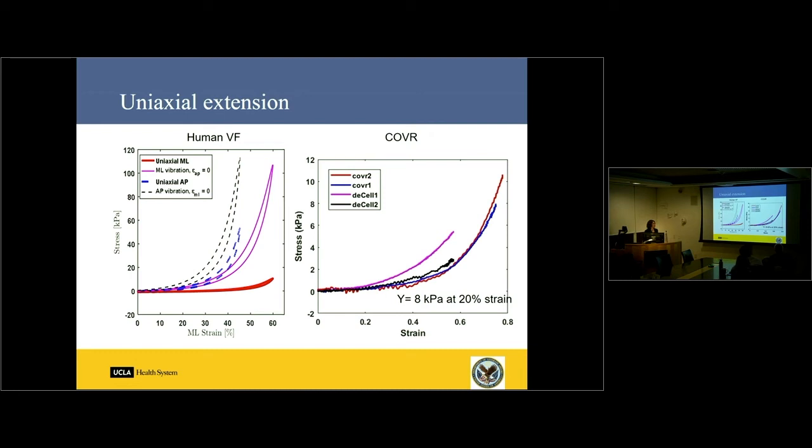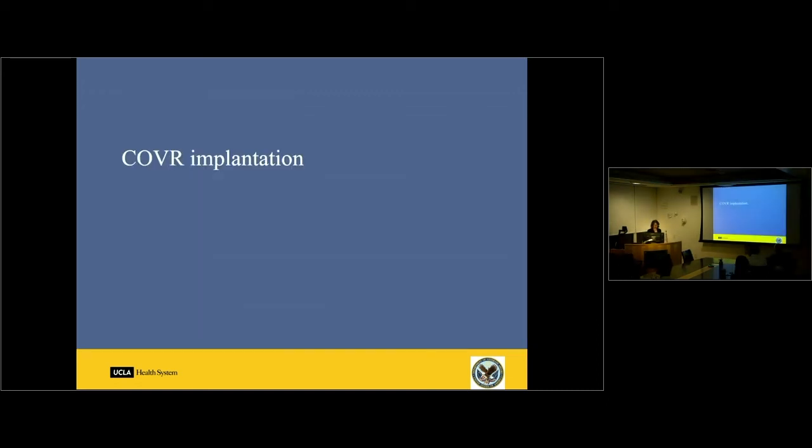We've done some experiments where we produce this gel and then remove the cells, treat it with the treatment, and eliminate all the cells. So then we are left with the mature matrix, but not the cells within it, and have tested that the stress strain behavior in that situation is reasonably close to the intact case. We'll talk a little bit more about that issue.